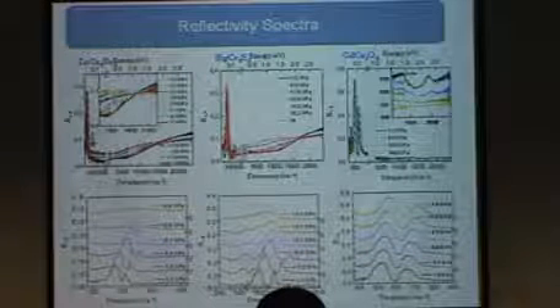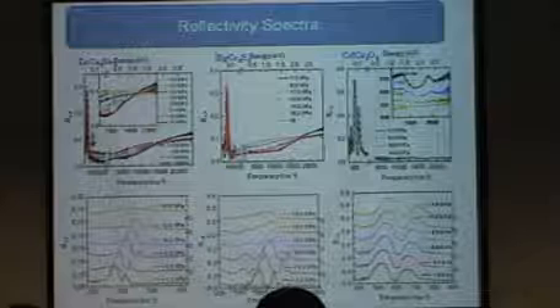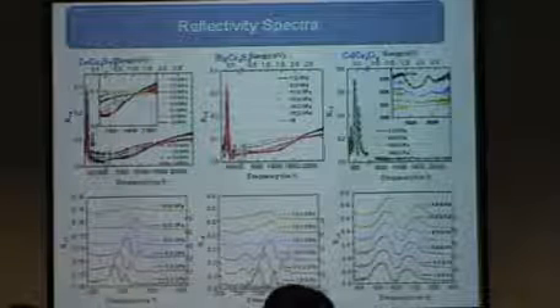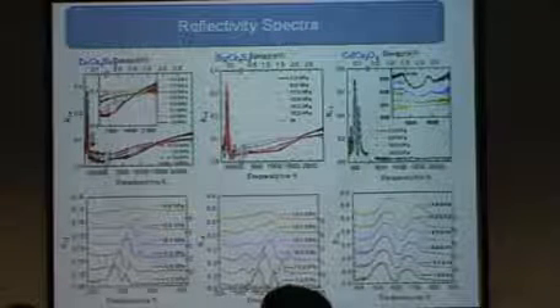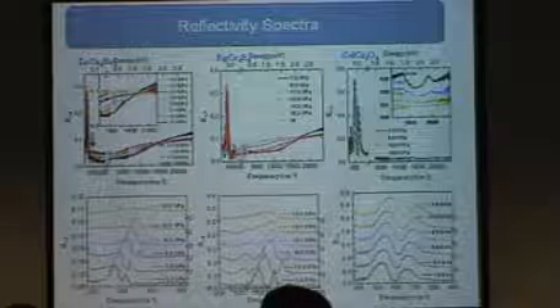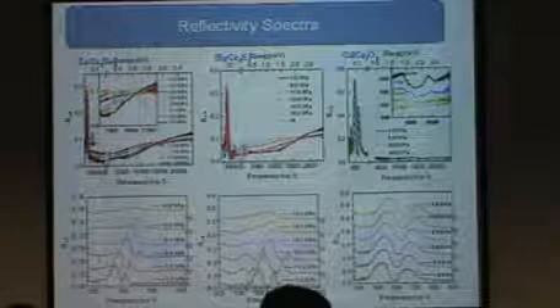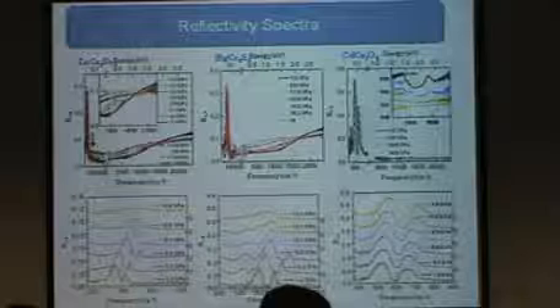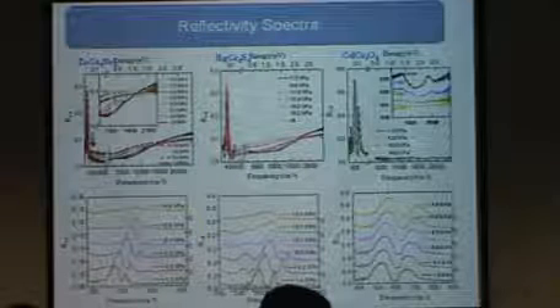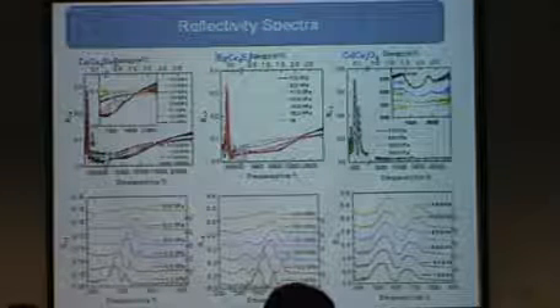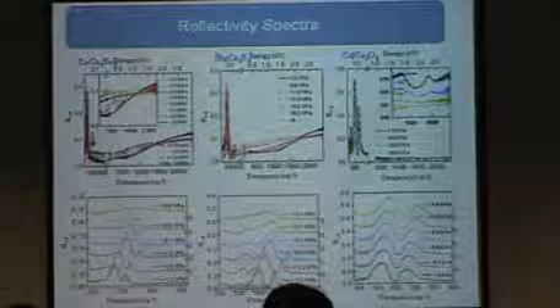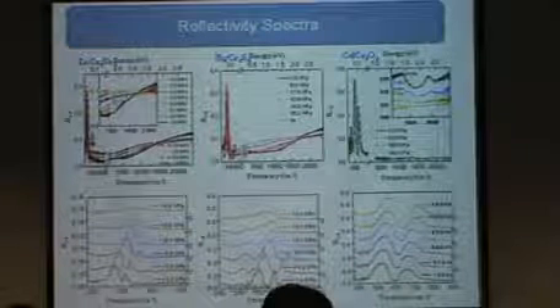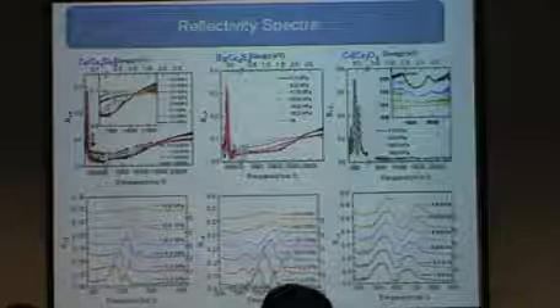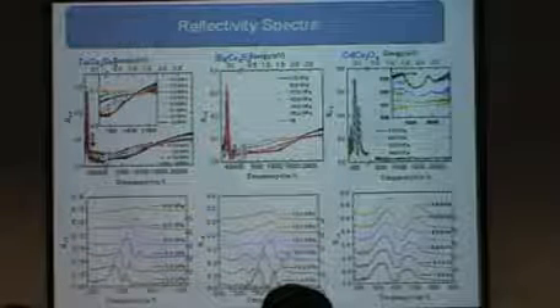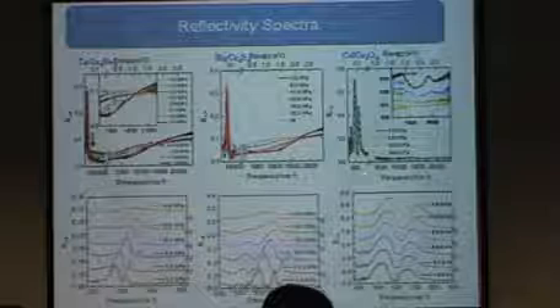Okay, here is the measured data of the reflectivity curve from 200 wave number to 25,000 wave number for all these three compounds, and this low frequency side is plotted separately so that one can see the pressure effect on the phonon modes. For sulfide and selenide compounds, with increasing pressure, the reflectivity level increases. But for oxides, you can't see any change in the reflectivity level in this high frequency range.